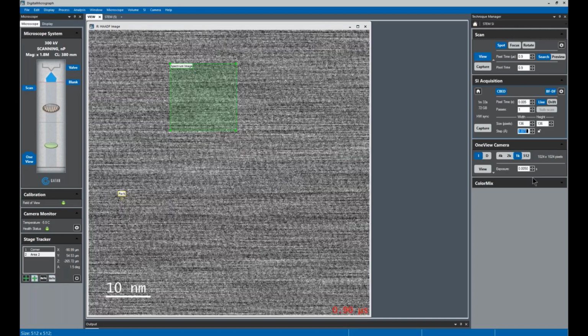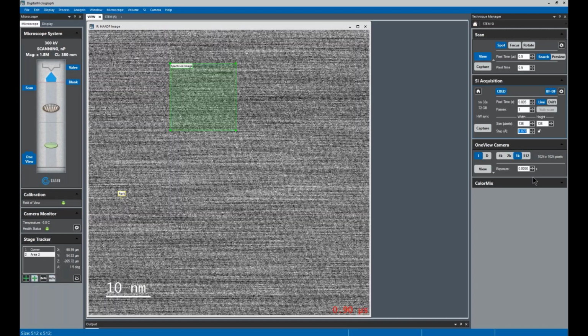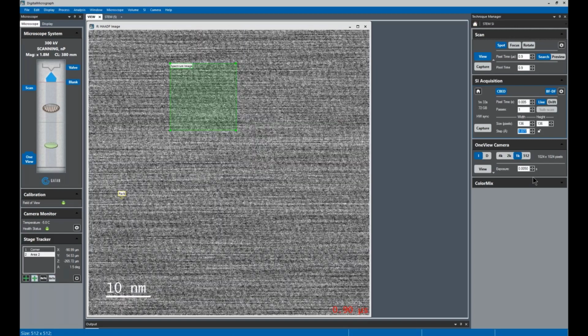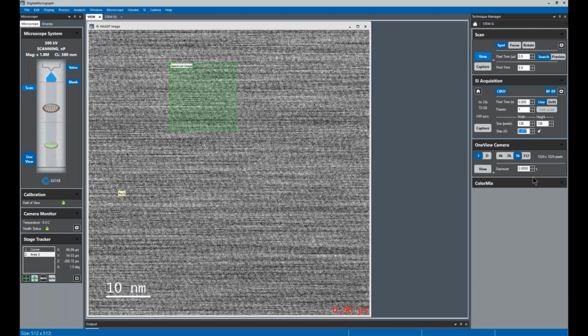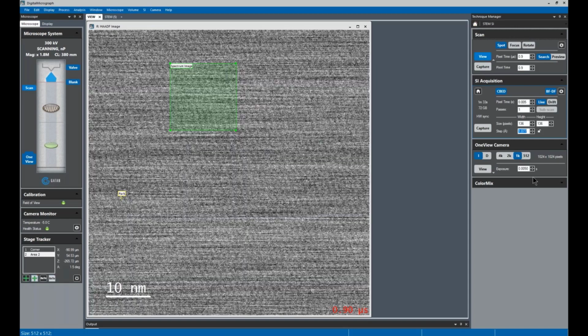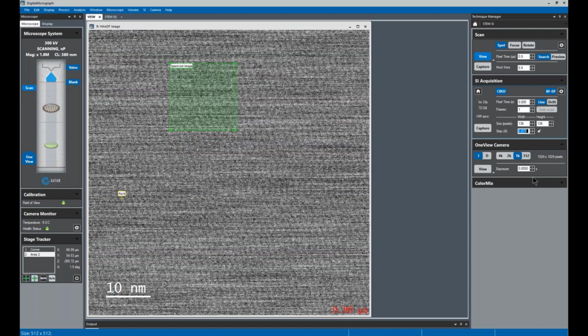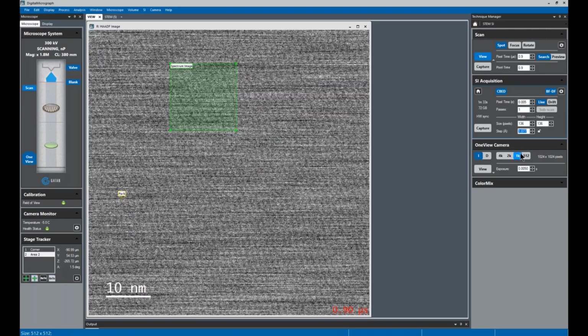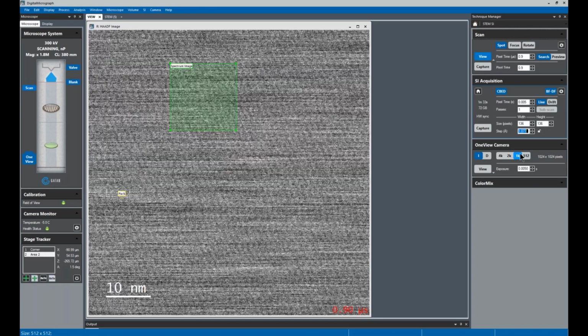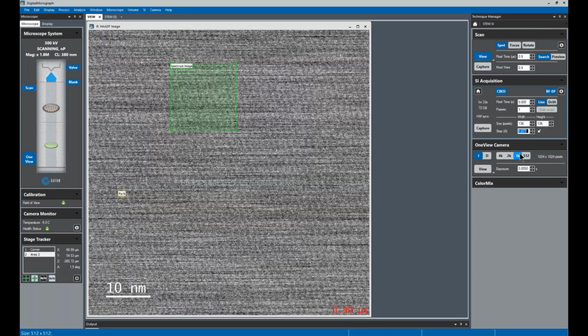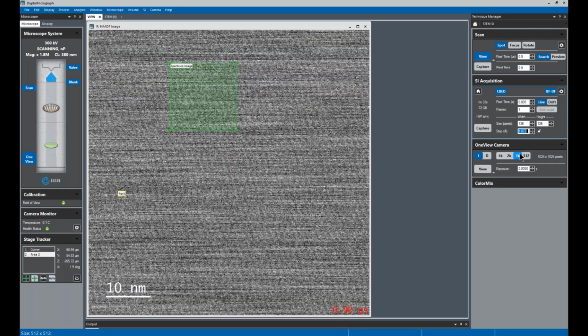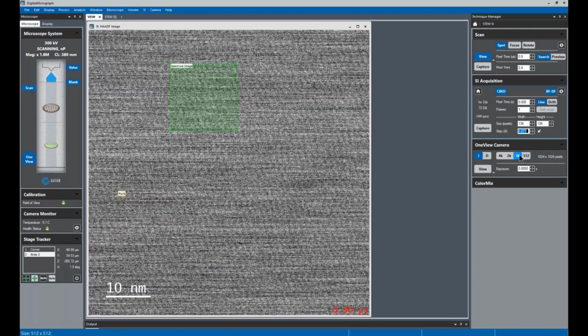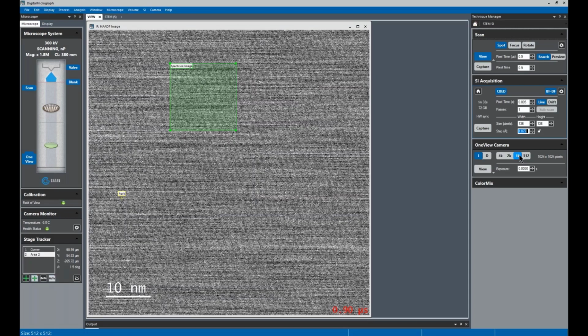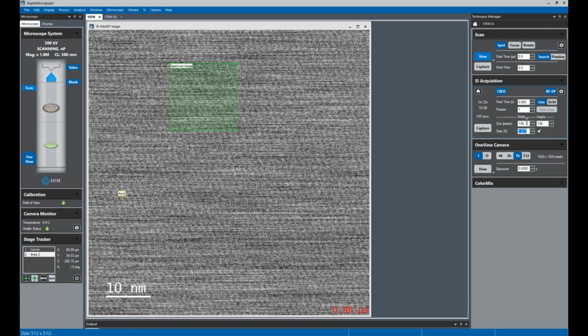The only thing you have to make sure of is, because many times we're looking at the center transmitted beam and at subtle changes in contrast or something in the diffraction features, that this image is high enough resolution to capture those features in the diffraction pattern. So that's the trade-off when you're thinking about things, especially with a camera like the OneView camera. Obviously with the Stela camera, you can go way faster, so it's less of a concern. But one of the things I think we checked is we'll make this 128 by 128.